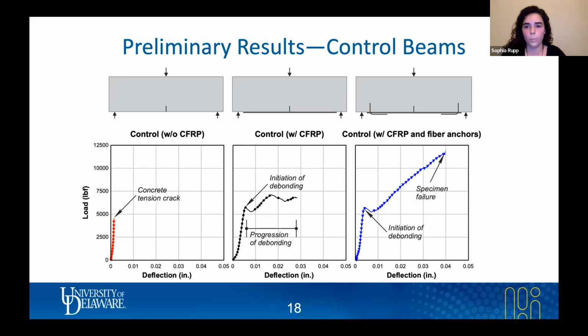And then for the beam that was strengthened with fiber anchors, you do see that initiation of debonding around the same load as you do for the beam without anchors. However, after that initiation of debonding starts to happen, you see a very significant increase in stiffness in the member, as well as increase in the load.